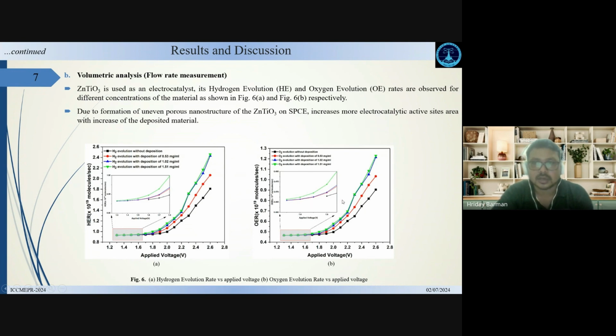Inside the graph, we can see it is clearly visible that after 1.6 volt it comes into action. But when we deposited the material on the SPCE, we are getting the flow rate at about 1.3 volt, starting at 1.3 volt. So when we use the bare electrode, the hydrogen and oxygen flow rate is lower, but after the deposition of the material, we are getting higher hydrogen and oxygen evolution rate, as we can see in the figures.